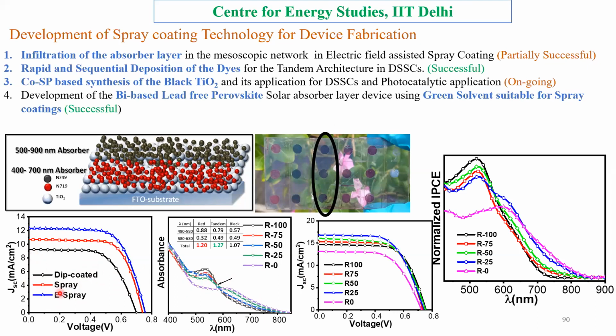But with the spray coating itself, let me talk in terms of JSC. If JSC improves, efficiency definitely improves, because overall efficiency is very much dependent on JSC and VOC and also fill factor. But in this case, if I am using the same material, everything is the same, VOC and fill factor will not change much, and JSC will change. So JSC is improving up to 11 milliampere per centimeter square. And when I am spraying, as I told, we are putting two electric fields. So with the second electric field, it improves as high as 12 milliampere per centimeter square. And this efficiency enhancement, you will not believe, is up to 55% just by using one small technology. It costs around 1,70,000.